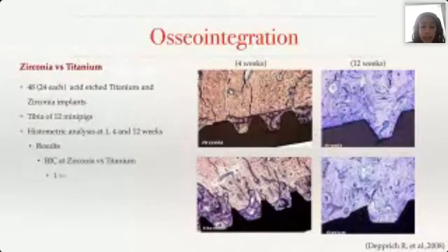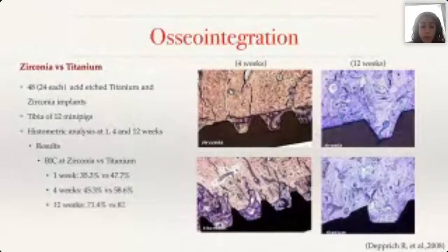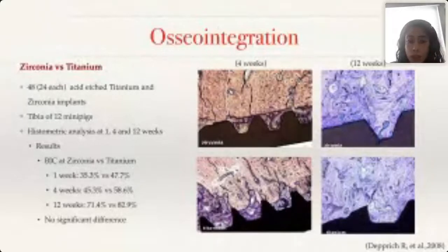They showed bone to implant contact of 35 versus 47% at 1 week, 45 versus 58% at 4 weeks, and 71 versus 83% at 12 weeks. So there was no significant difference in osseointegration between zirconia and titanium implants, according to this study.